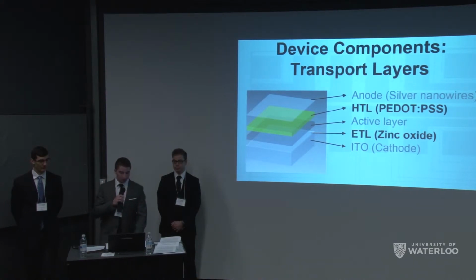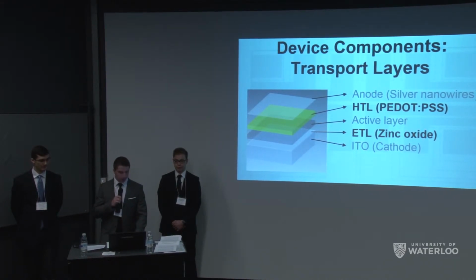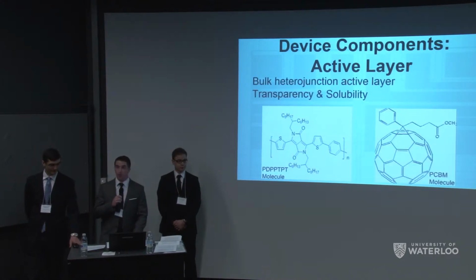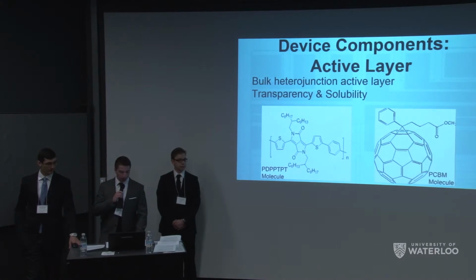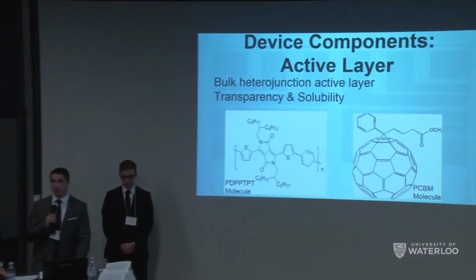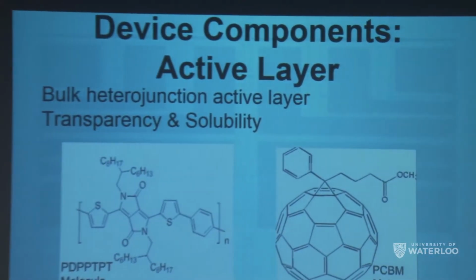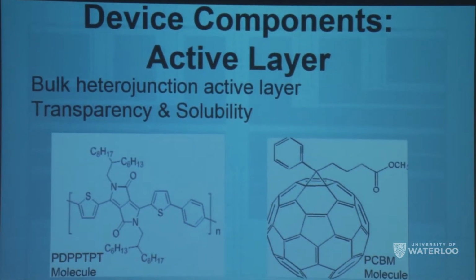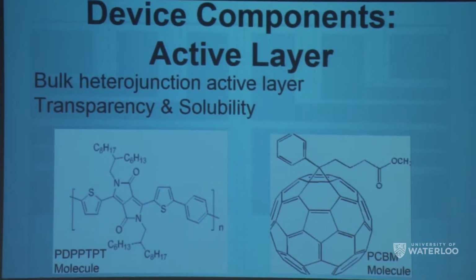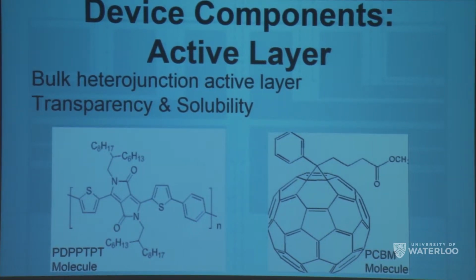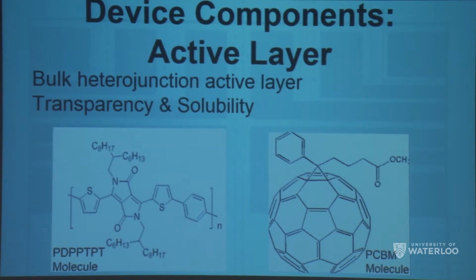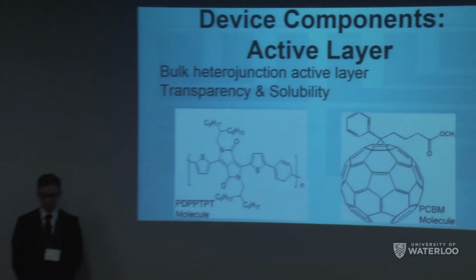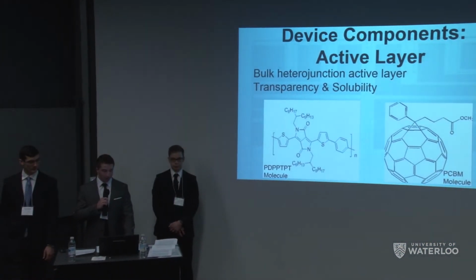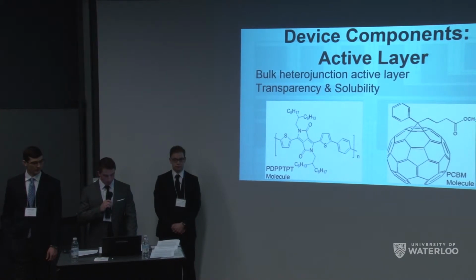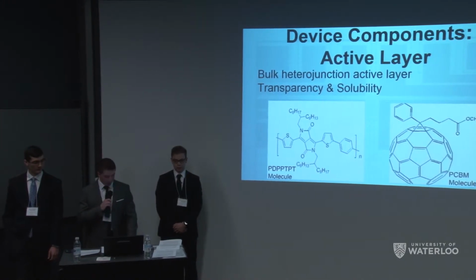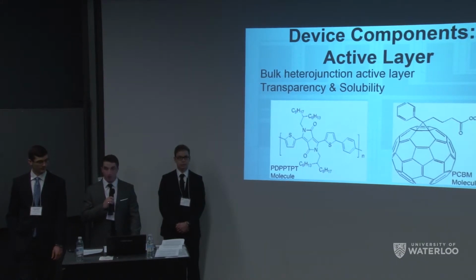Our active layer is a mix of two materials that form the bulk heterojunction. That is to say, this is the part of our device that actually absorbs light and generates electricity. For our electron donor, we chose to use a polymeric material called PDPP-PT-PT, which is a thiophene copolymer, and the name is very long. This is a long polymer with each molecule containing many of the chromophores that allow electrons to be excited. We chose a polymeric approach instead of a small molecule approach, which is traditionally used in organic solar cell research, because polymers dissolve better in solution, making them much more readily adaptable to solution processing methods. Our electron acceptor was a fullerene material called PCBM, and this was chosen because of its transparency and solubility.